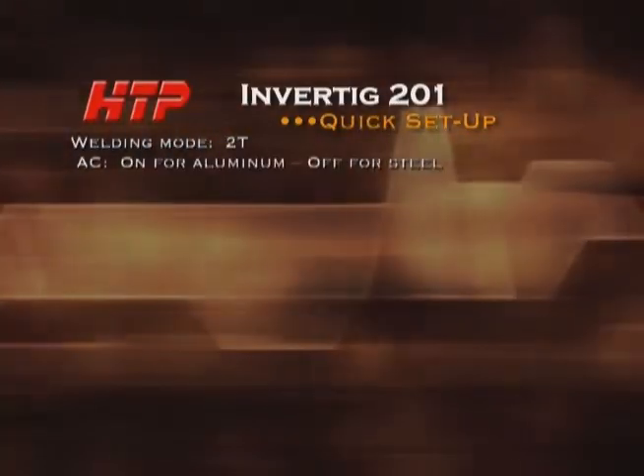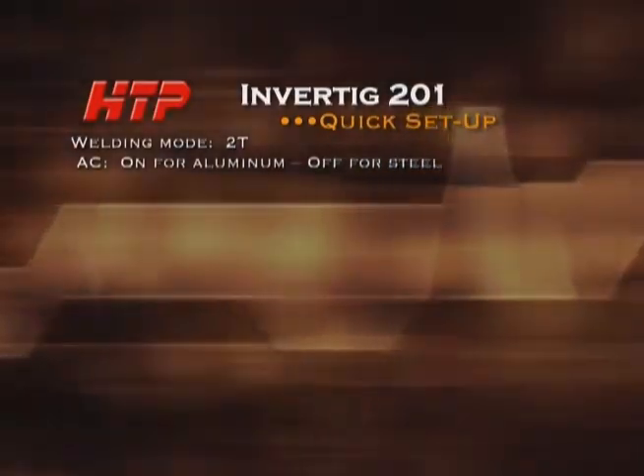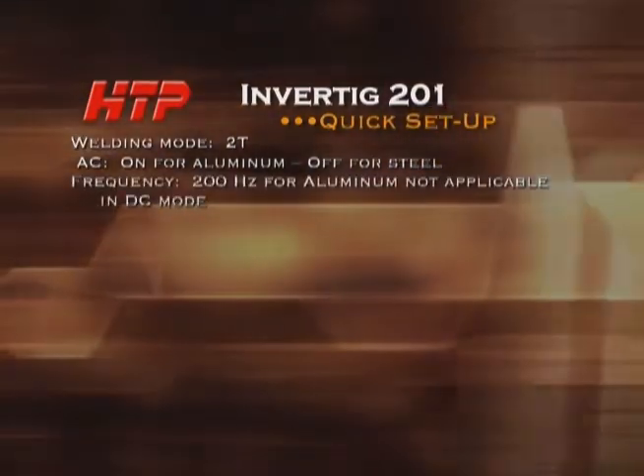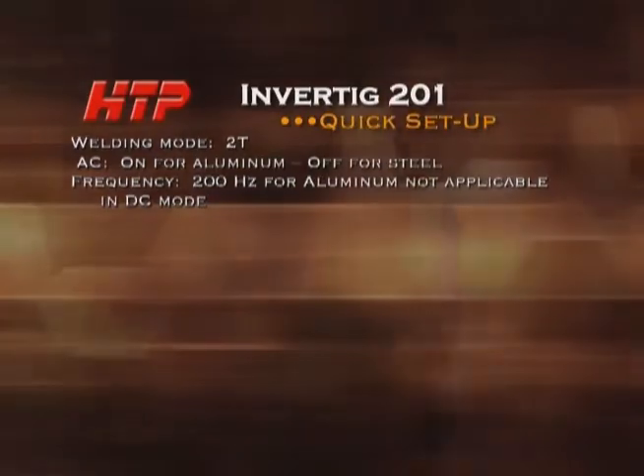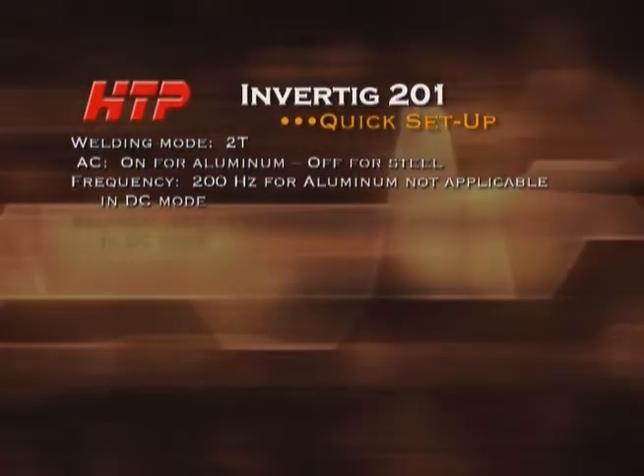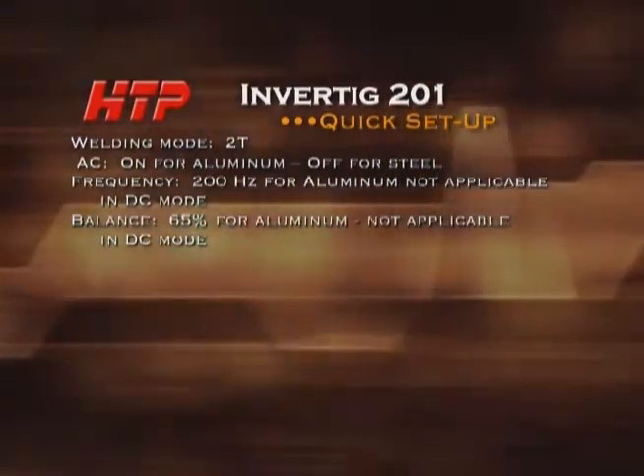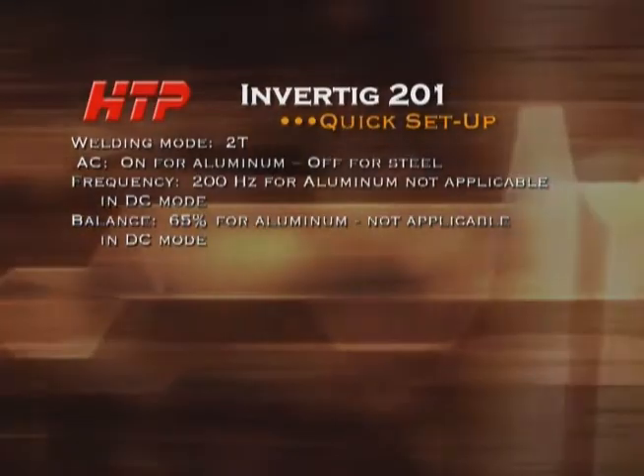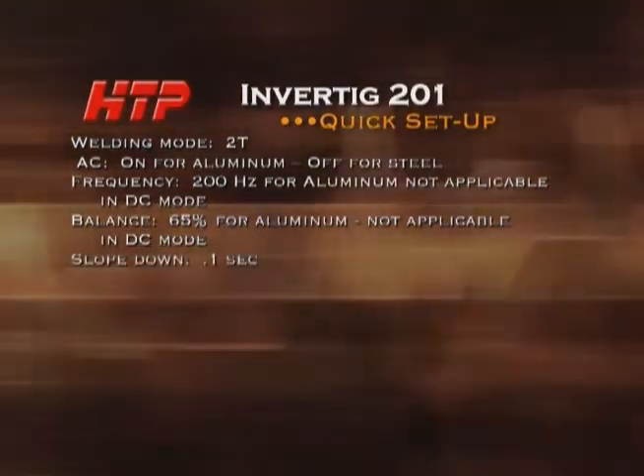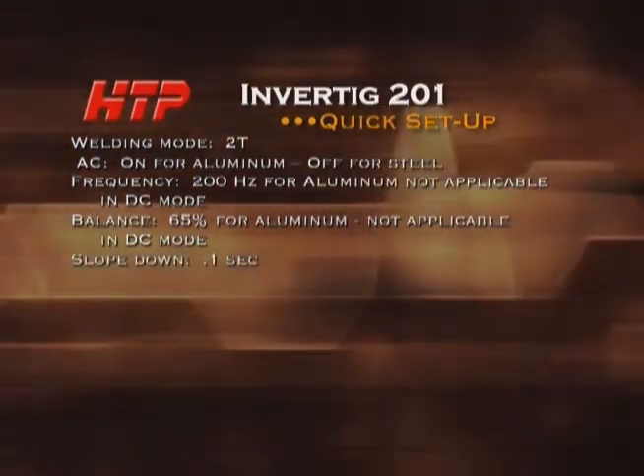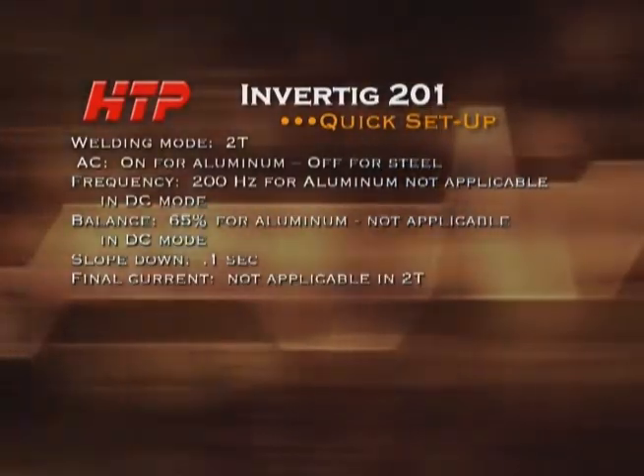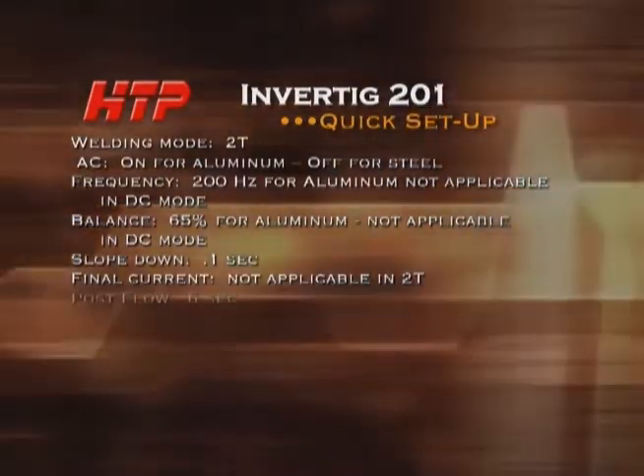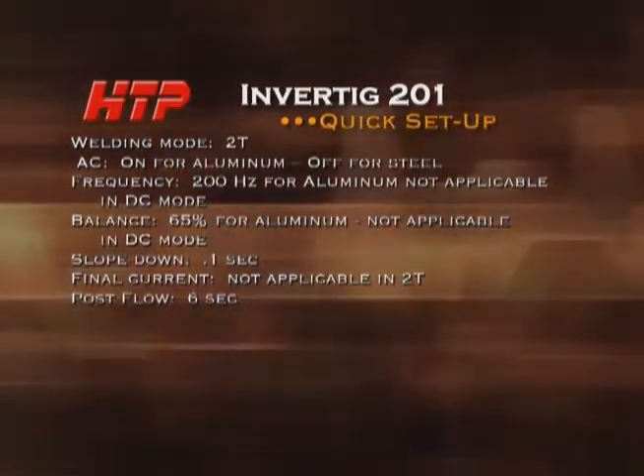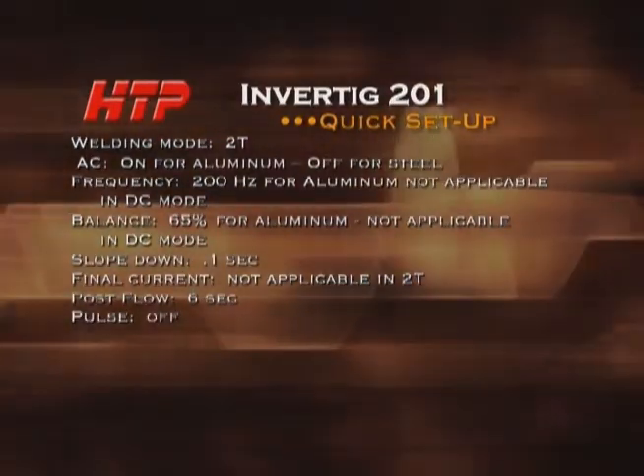Welding mode 2T. AC: on for aluminum, off for steel. Frequency 200 Hz for aluminum, not applicable in the DC mode. Balance 65% for aluminum, not applicable in the DC mode. Slope down 1/10 of a second. Final current, not applicable in 2T. Post flow 6 seconds. Pulse off.